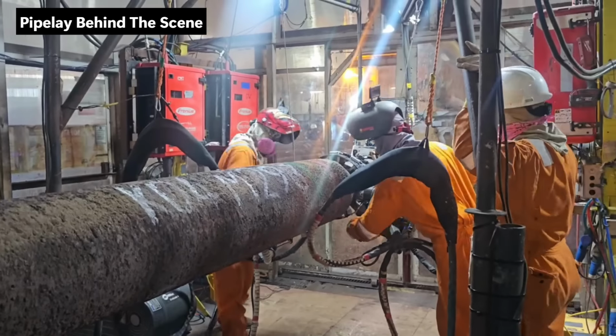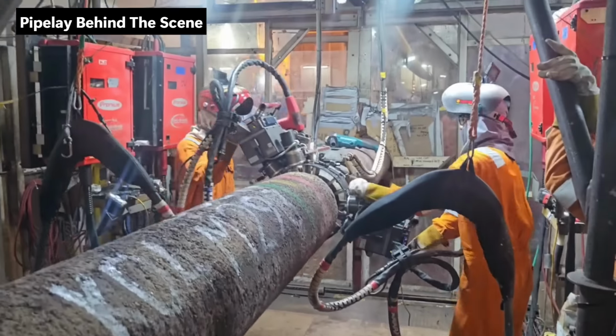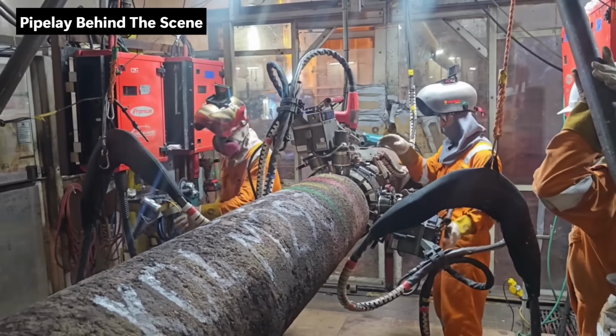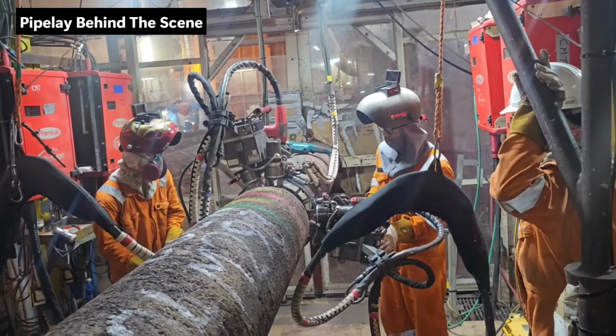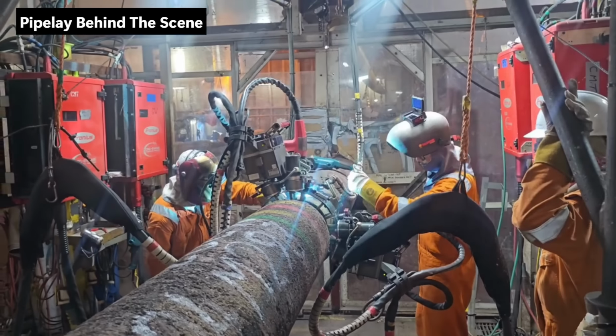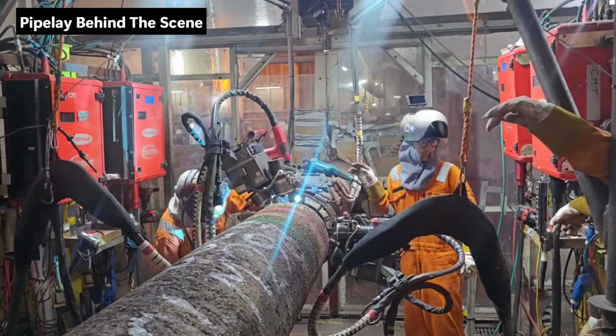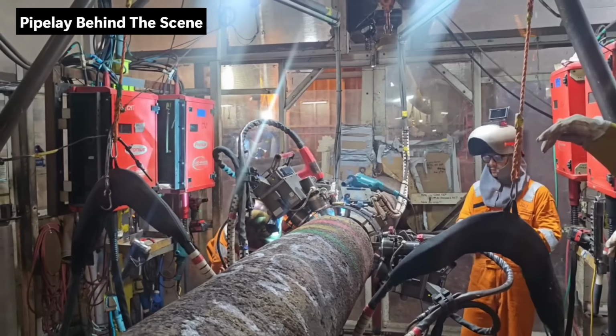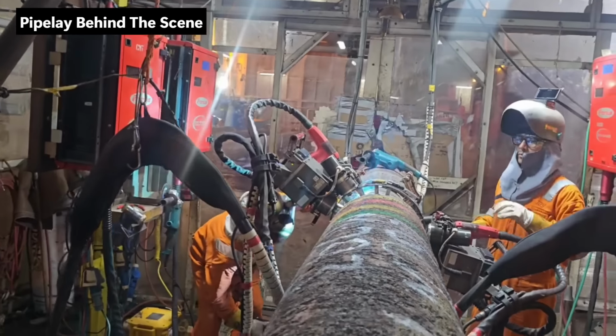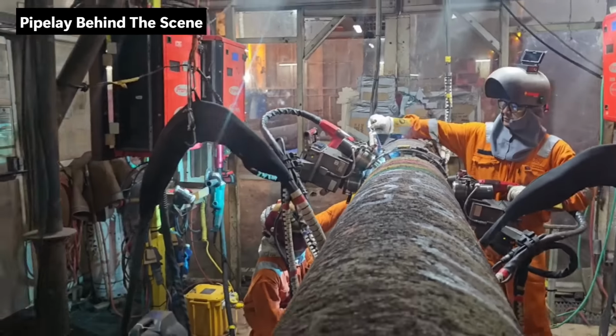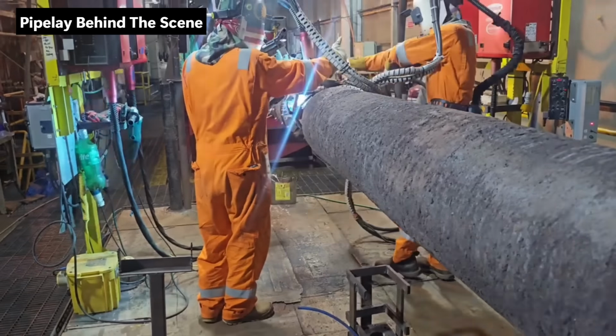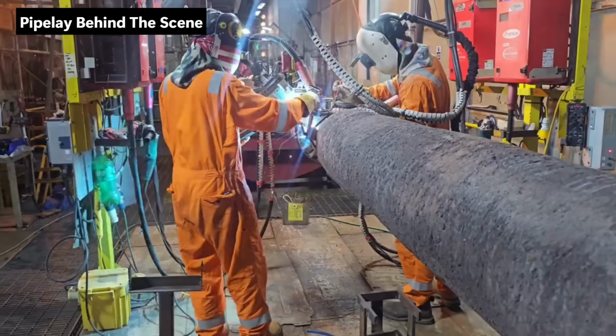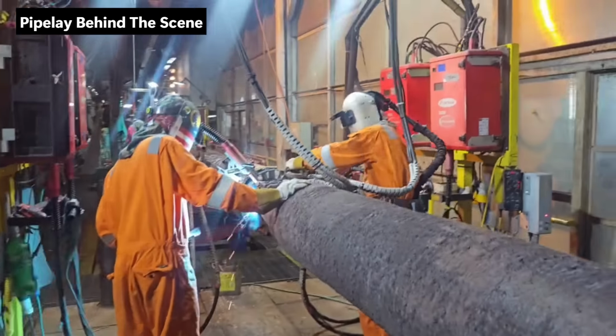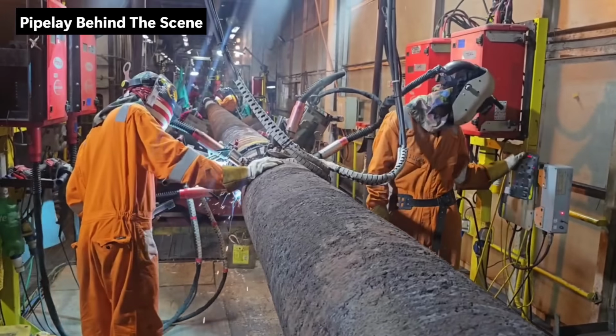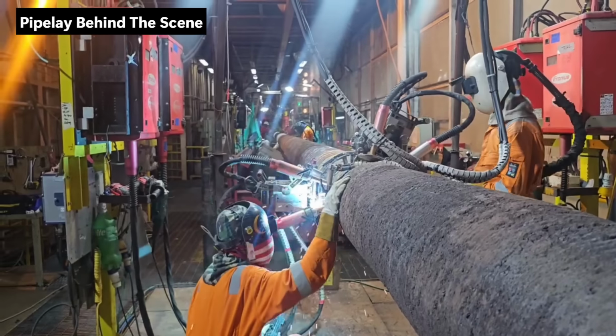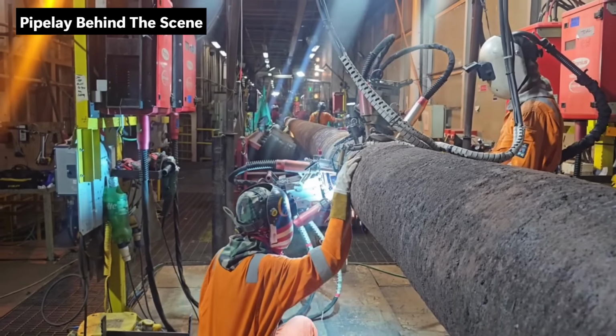Station 1 puts down the root pass. This is the first weld bead that actually joins the two pipe ends. It is the most critical pass of all. If the root pass has a problem, every pass on top of it inherits that problem. Station 2 follows with the hot pass. This builds on the root, adds more weld metal and starts filling up the bevel.